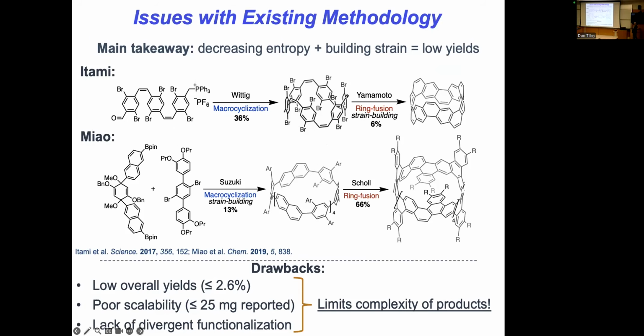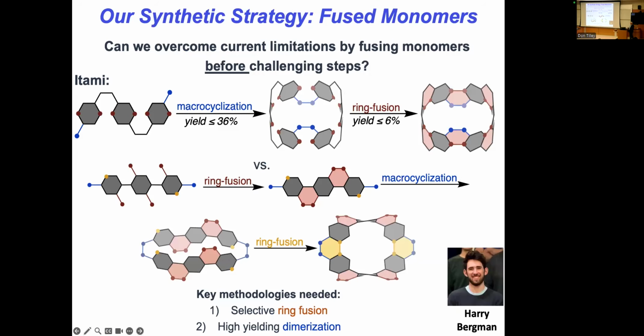So these syntheses are challenging and inherently low yielding, and that's because you have to build in a lot of strain. So inherently, these groups are using coupling reactions like the Yamamoto coupling here, that introduces a lot of strain, and you lose a lot of degrees of freedom in one reaction. So of course the yield is going to be very low. Here a Scholl reaction is used for doing that. And that's why the yields of these species have been less than 3%, and only milligrams of each have been made. So we thought that we could use the ring fusions and the macrocyclizations in a productive way to make a nanobelt. And this is the work of Harry.